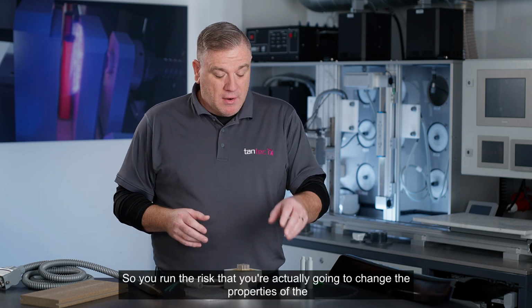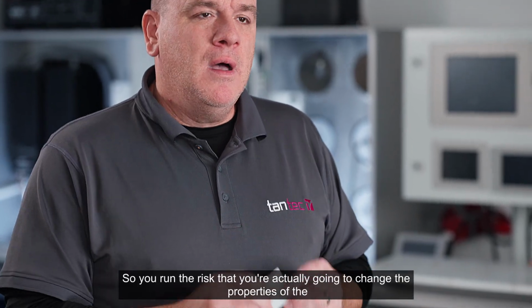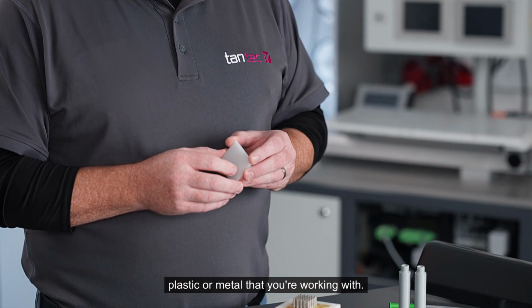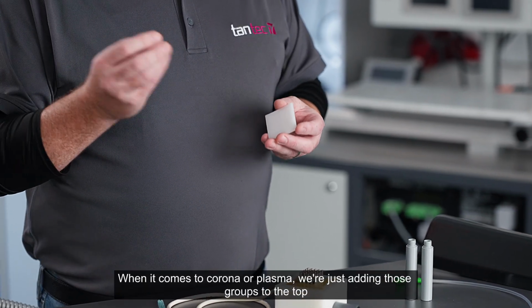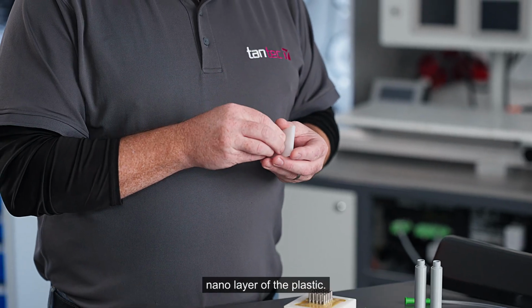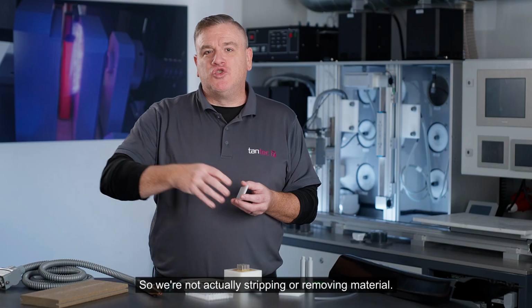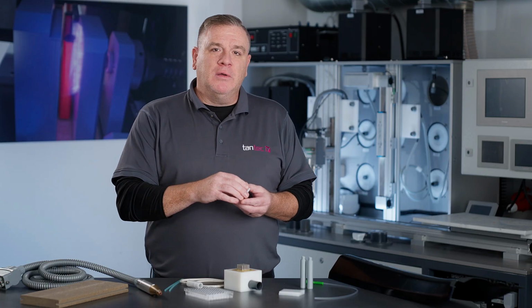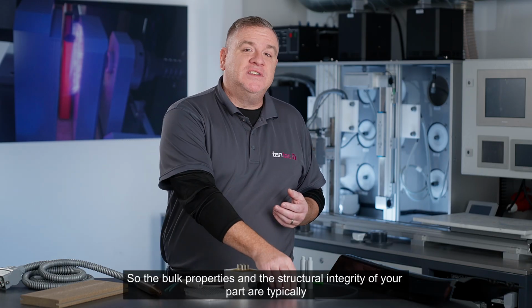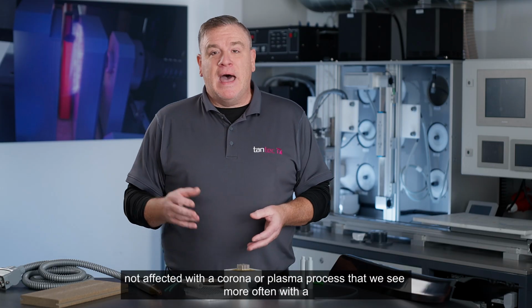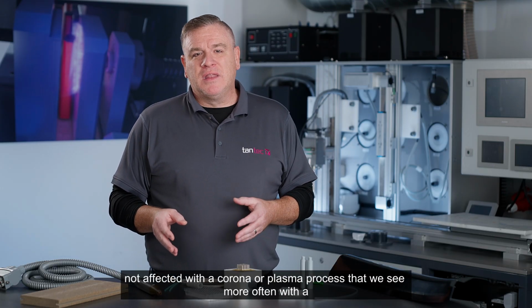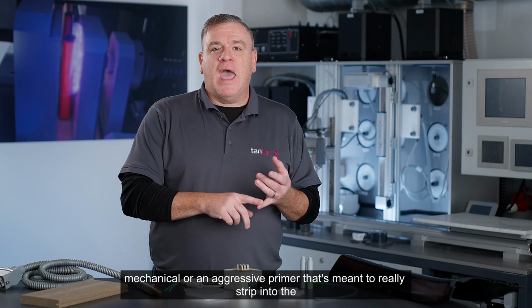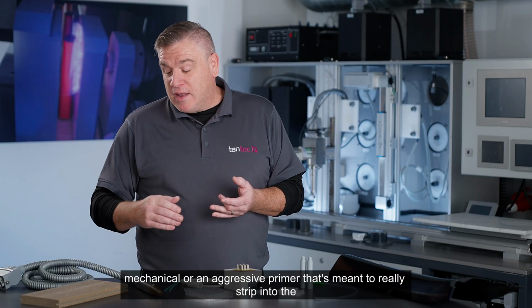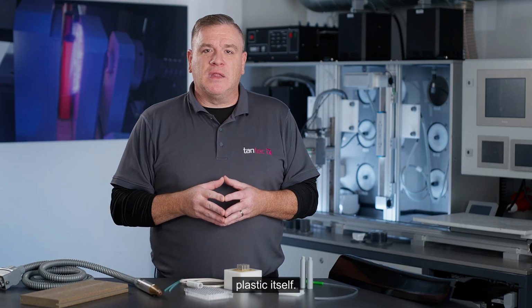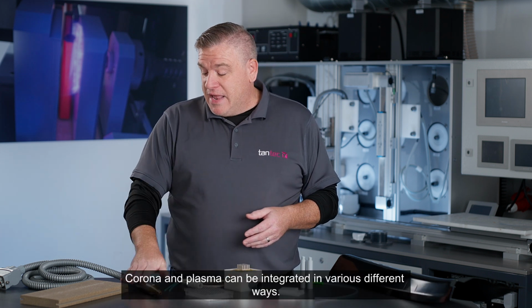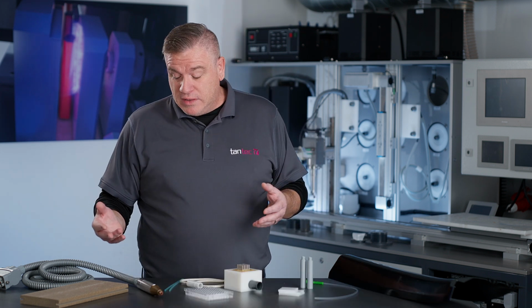So you run the risk that you're actually going to change the properties of the plastic or metal that you're working with. When it comes to corona or plasma, we're just adding those groups to the top nano layer of the plastic. So we're not actually stripping or removing material. So the bulk properties and the structural integrity of your part are typically not affected with a corona or plasma process that we see more often with a mechanical or an aggressive primer that's meant to really strip into the plastic itself.